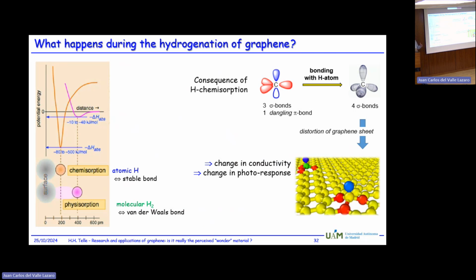the conductivity of the sample. Because if you take graphene, where you have your pi bond, which is dangling, the pi electrons can move freely through the graphene. So that means it's a very good conductor. If all of a sudden, by a bond, you take away this free moving electron, it's quite clear that there is less current flowing and there's a higher resistance of the system. So basically, you can immediately tell, if you measure Raman spectra and conductivity of the sample, whether you have attached hydrogen or not.